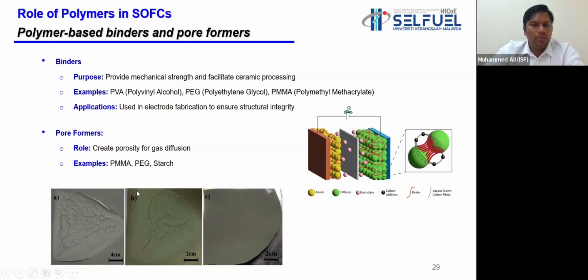I've given some examples of when we are not adequately using the binders. You see some cracks on the surface of the films. This is a film actually. We produce some tape cast films, and then we subject them to a sintering process, and then we can see some cracks on the surface of the fabricated films. To avoid these cracks, we have to use the right amount of binders, surfactants, and plasticizers to improve the structural integrity of our films. So this is one of the best recommended areas where you can do research related to binders.